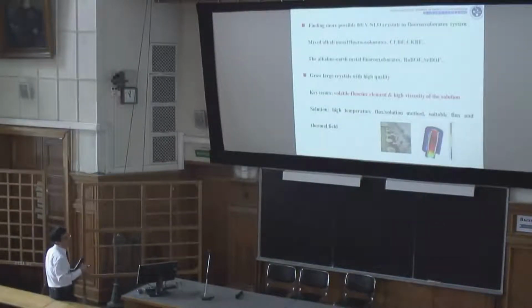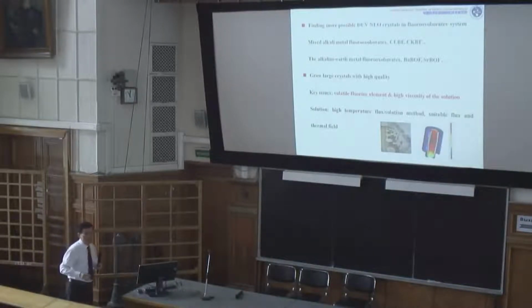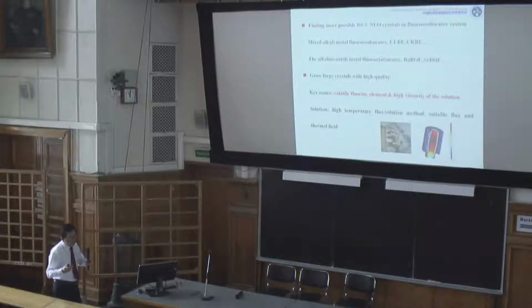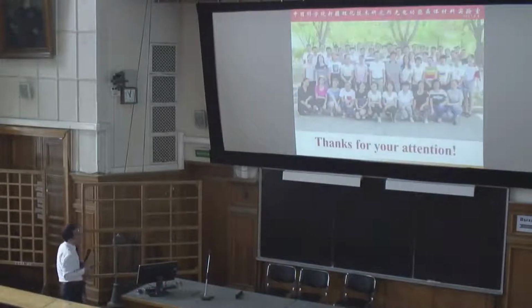Next, we want to search for new compounds with excellent, interesting properties and grow large crystals of high quality. Of course, this kind of crystal may be challenging to grow because in this kind of system there are volatile fluorine elements. Also, for fluorine borate systems, the viscosity is high, which means the particles cannot transport, so it cannot grow large crystals. So next we want to use the high temperature flux method, search for suitable flux and thermal fields, and grow large crystals.